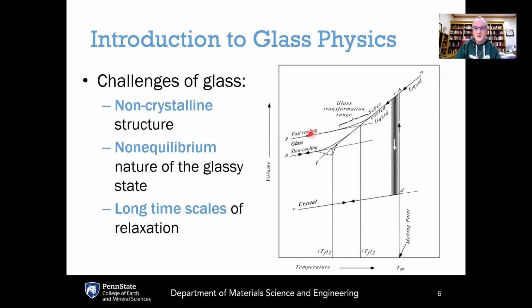And like a liquid, a glass still has a viscosity. It is a very high viscosity, but it is an intrinsic property of the glass. And if you wait long enough, or if you heat up the glass, you can observe that the glass will, in principle, flow over time. Now, this connection between the glass and the liquid state is called the glass transformation range or the glass transition range. The transition between the supercooled liquid and the glass is a gradual freezing in process.